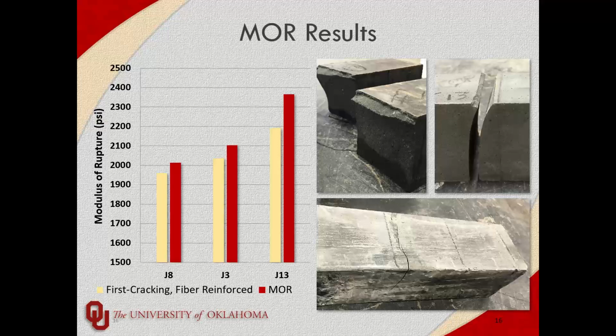But the most interesting thing I'd like to note on this is that we did reach pretty high levels of modulus of rupture, even for a UHPC. The first bar on the plot is the first cracking, so it's not even the ultimate strength. We wanted to evaluate how much those fibers helped up to cracking, and it didn't seem to help much at all.